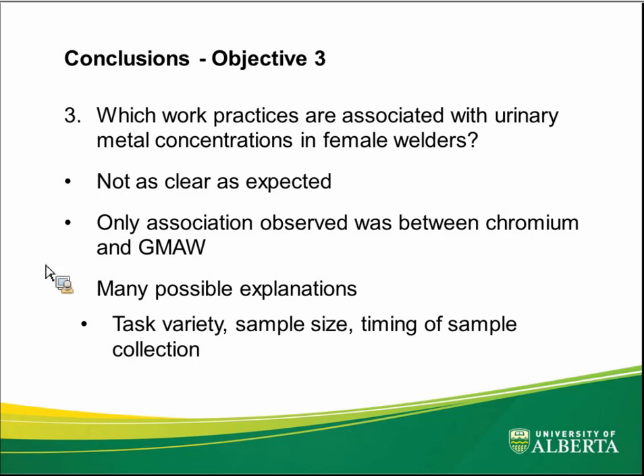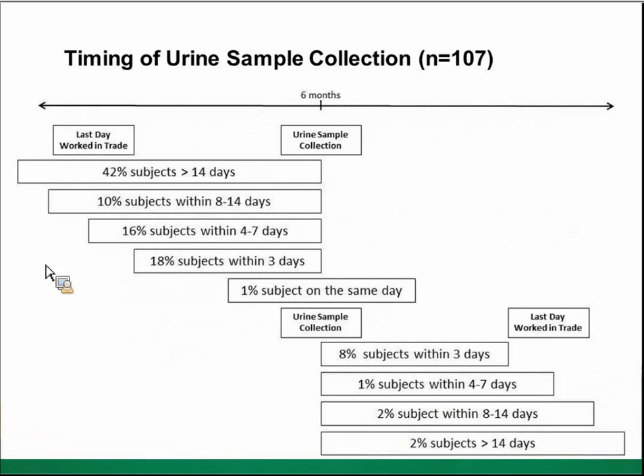And which work practices were associated with these metal concentrations? Really, these results were not as clear as we had hoped. The only association was between MIG welding and chromium. There are many possible explanations for these null findings. One is the task variety: they were doing multiple things on their last day of work, and perhaps we're unable to classify their exposure correctly simply by the type of welding that they were doing. The sample size is the other problem, because we can't really classify their exposure much beyond that without running into sample size issues with 45 women. And the third challenge was the timing of the sample collection. We knew that the urine sample had not been collected in that window of exposure that we were most interested in, and we couldn't know that until we got the data.